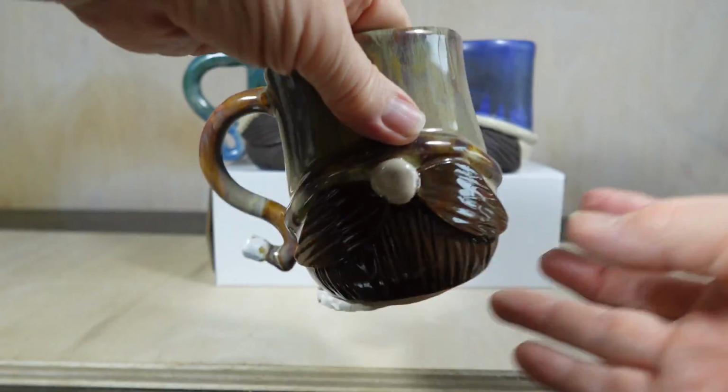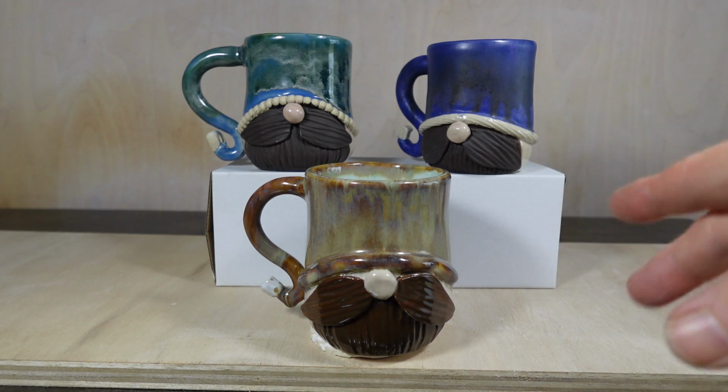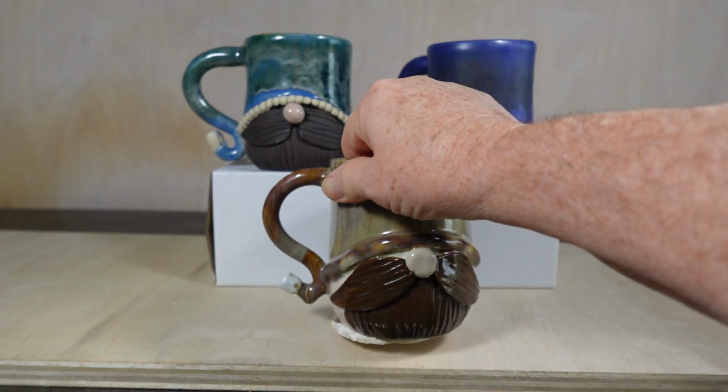I'll fix that up. So it originally was SW214 Micro Pearl, only 1.5 times, and then SW216 Micro Jade 1.5 times, and I don't think I put enough on. I was afraid it was going to run, but it was just very dull. It wasn't very exciting at all. So I added Ferric Fever over top from Pottery Supply House, thinking that it wasn't going to run. I was wrong, but it came out really pretty.